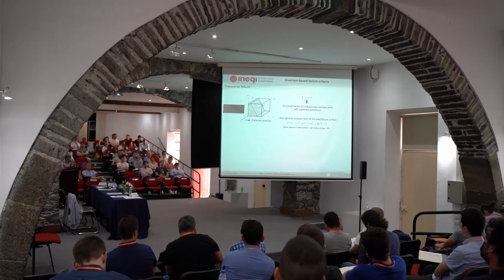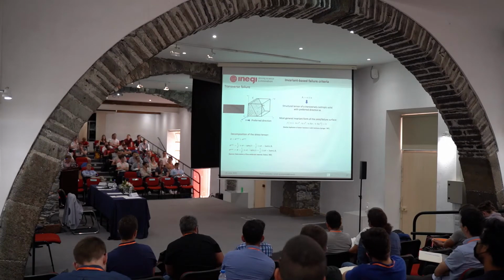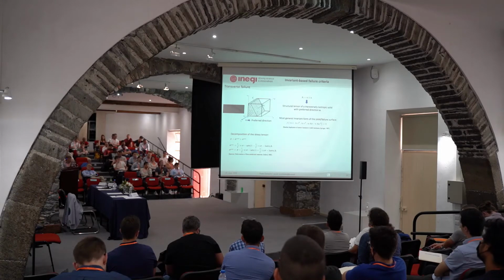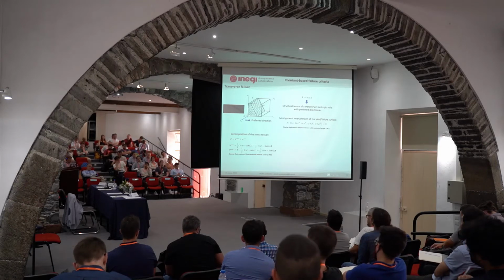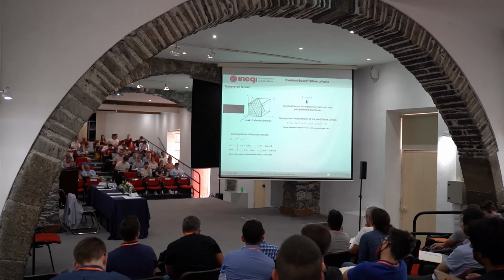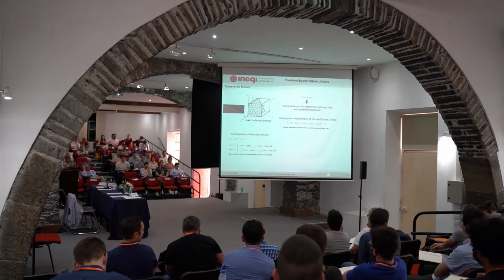Okay? So this is the most general form, and here we can use the stress tensor or components of an additive decomposition of the stress tensor. And this is exactly what later on Spencer did, where he proposed a decomposition of the stress tensor into what was back then called a plasticity-induced component of the stress tensor, P int, and the reaction stress tensor. So P int is formally calculated, imposing that its projection into the fiber direction is 0, and that its trace is also 0.